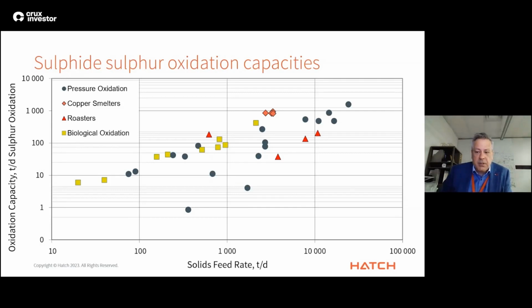Copper smelters tend to be clustered around a solids feed rate of 3,200 to 3,300 tons per day and 845 to 937 tons per day of sulfide, likely due to the economies of scale. Roasters operate at higher solids feed rates of 3,800 to 10,800 tons per day, but much lower oxidation capacities of 38 to 200 tons per day of sulfide. Pressure oxidation tends to follow the same slope as biological oxidation, with both having a broad economic range of both oxidation capacity and ore throughput.